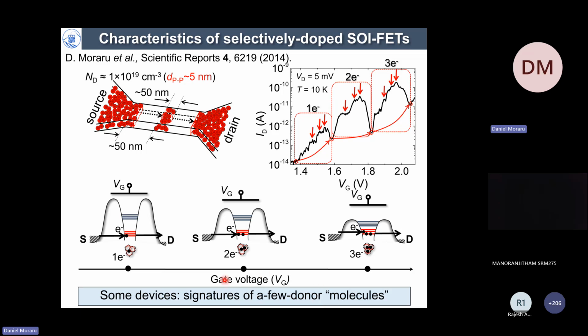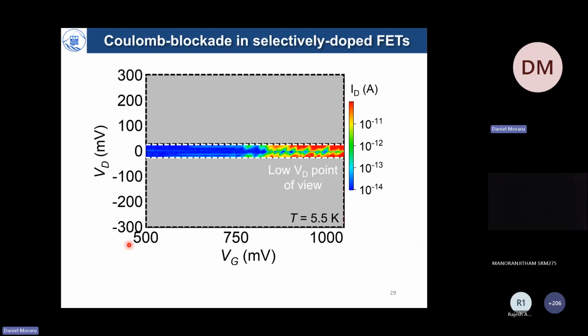The problem with this is that it's still at low temperature. So we were not successful in raising the operation temperature because the device was not optimized. However, we were successful in observing, at low temperatures, a lot of information about this kind of dopant molecule. So I'll show you a few more insights next, and these were obtained with my PhD student several years ago, and he measured the stability diagrams for this kind of device.